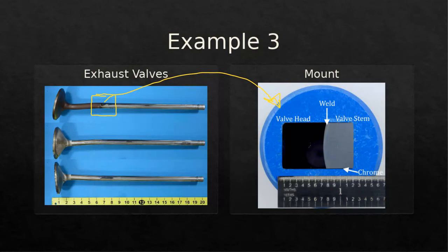The weld, you can see that after the sample has been etched, the valve head is unaffected by the etchant. It's still dark, which means the etchant did not work on that side, and I'll explain why momentarily. But then you have a very distinct line, and here's your base material, and I'm not sure if you can see, but there seem to be some linear indications that run in this direction, left to right. You kind of see some dark banded features.